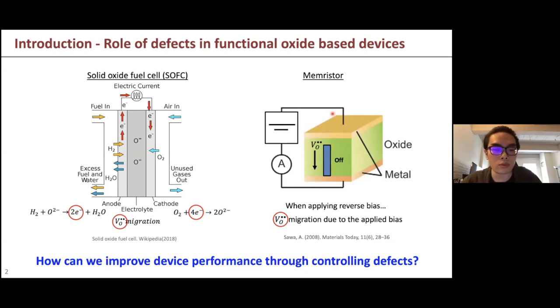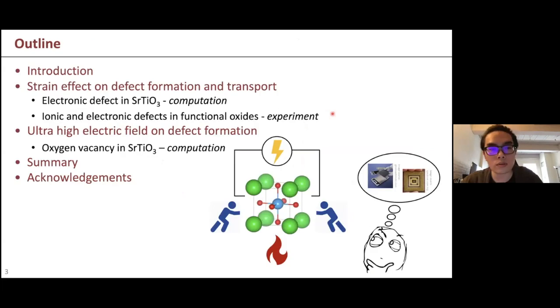So how can we improve the device performance through controlling the defects? In this talk, I'm going to break it down into three different parts. The first is how strain can affect both electronic and ionic defects. In this computational study, I will use strontium titanate as my model material. The second one will be an experimental demonstration, which can be applied to basically all kinds of oxides you're interested in, either a bulk material or a thin film material, or a thin film device. And the third part will be studying the ultra-high electric field effect on defect formation. And I again use strontium titanate as the model material.